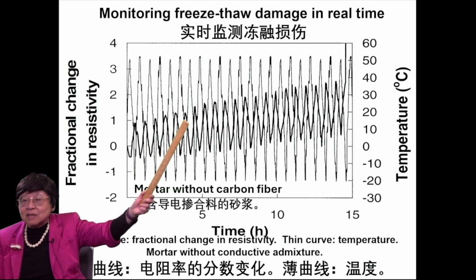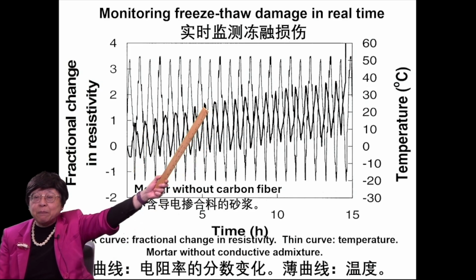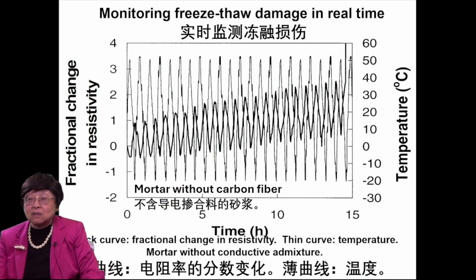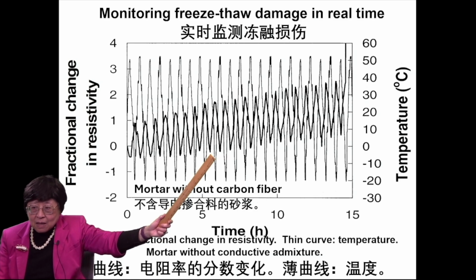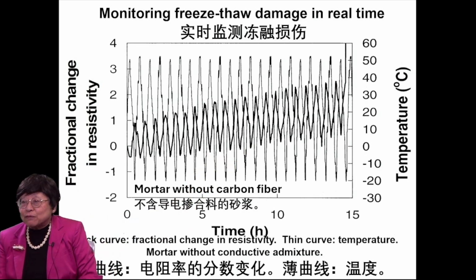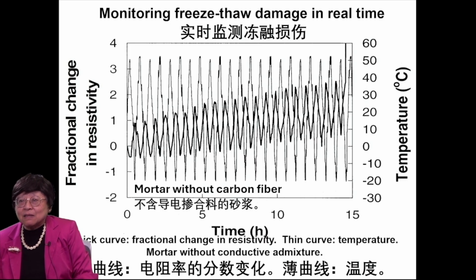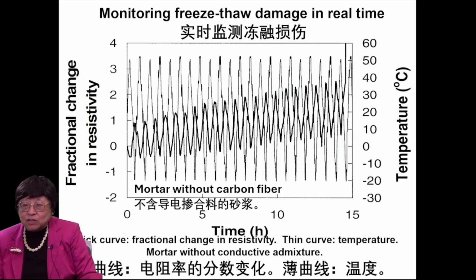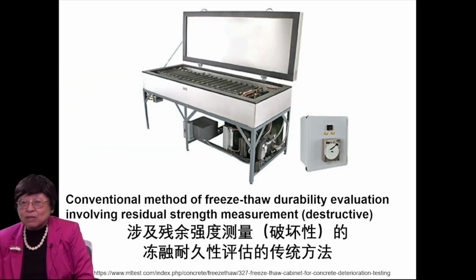But interestingly, there is this incremental rise in both the upper envelope and the lower envelope of the resistivity as the freeze-thaw cycling progresses. That means the damage due to the freeze-thaw cycling occurs in every cycle until at the last cycle, it dies or fractures at the coldest point of the last cycle. And this is the first time that freeze-thaw damage is monitored in the entirety of the freeze-thaw life in real time. Traditionally, people don't do it in real time, but they evaluate by measuring the residual strength, how much strength is left after so many cycles of freeze-thaw cycling. And that's not very sensitive.